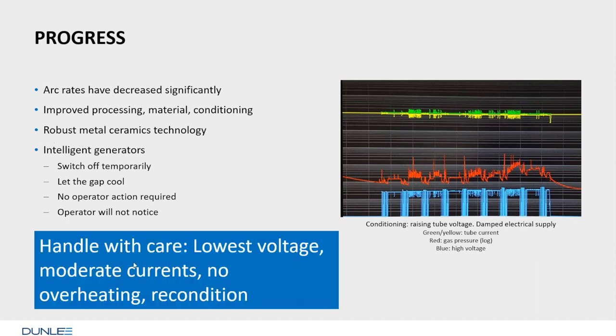If a tube is under operation, what we have to do is handle it with care. Don't overstress the voltage ratings. Use moderate currents, no overheating, and in some cases, it is advised to recondition the tube. And you see here the last voltage is a little lower than the previous, and you see already an improvement. This is part of the conditioning process.